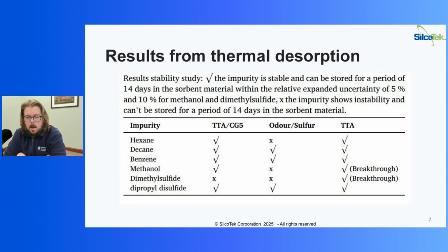And you can see amongst all three here, the TTA was the one that worked the best, although they did see some methanol and dimethyl sulfide breakthrough. And so the breakthrough just means that it didn't fully get sorbed on the tube. They had a couple of tubes in parallel, and some of the methanol and dimethyl sulfide actually got sorbed on the secondary tube rather than on the first primary tube.